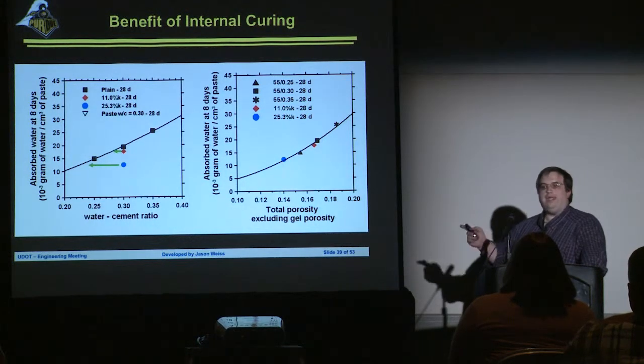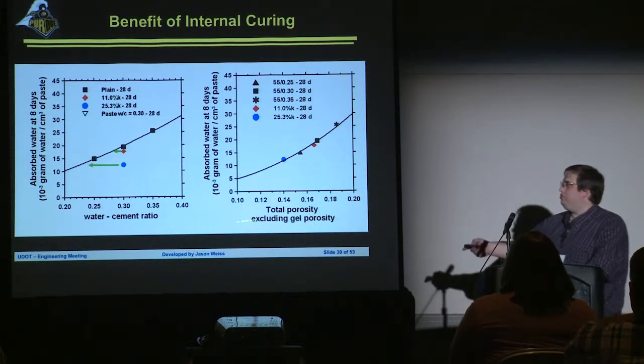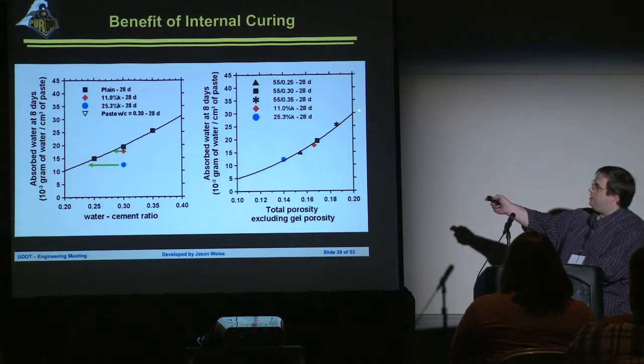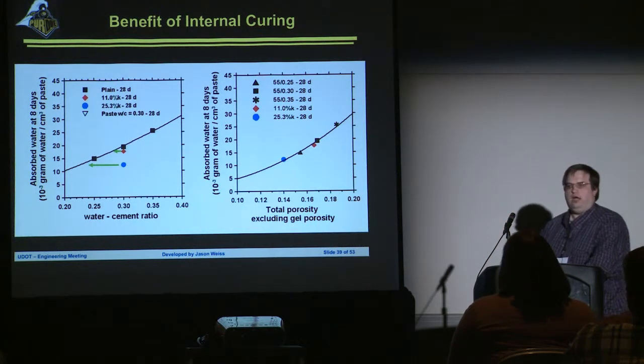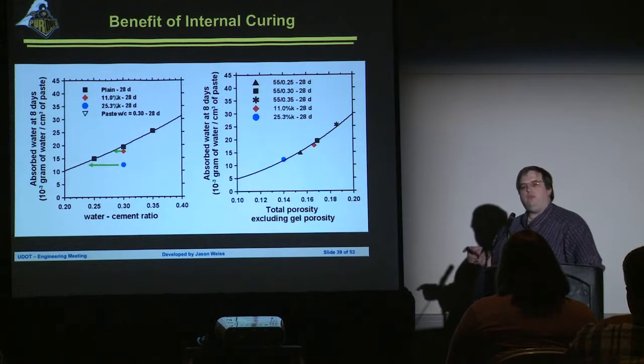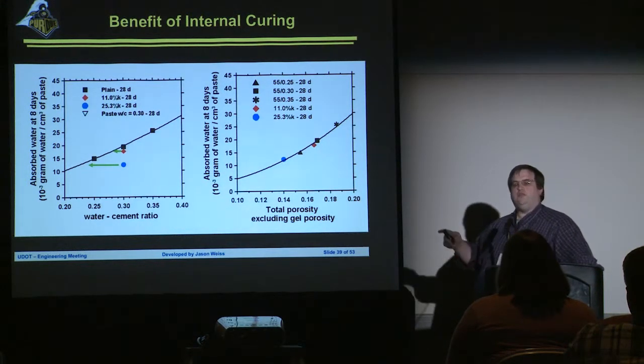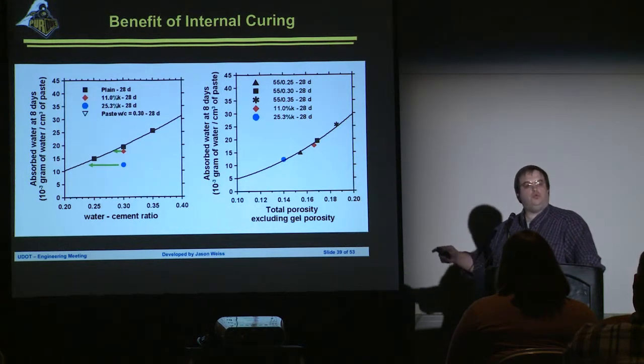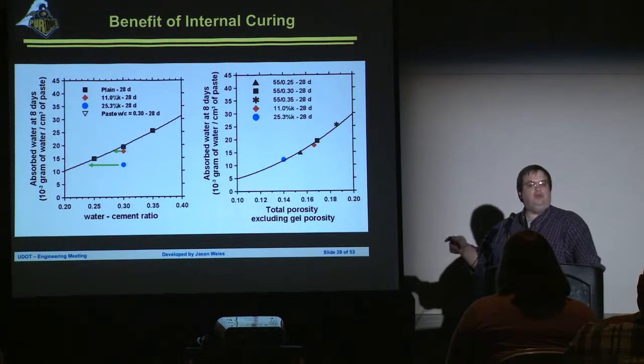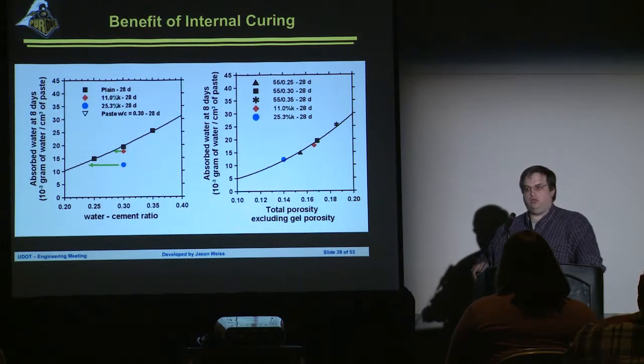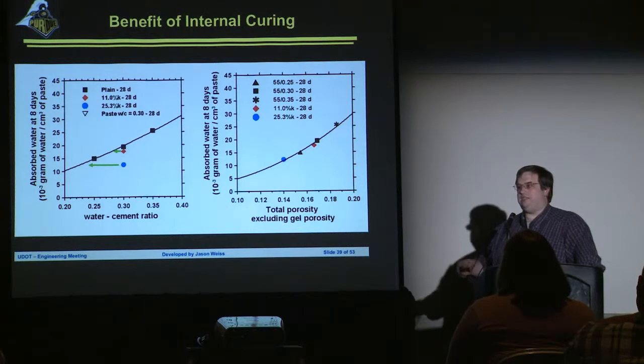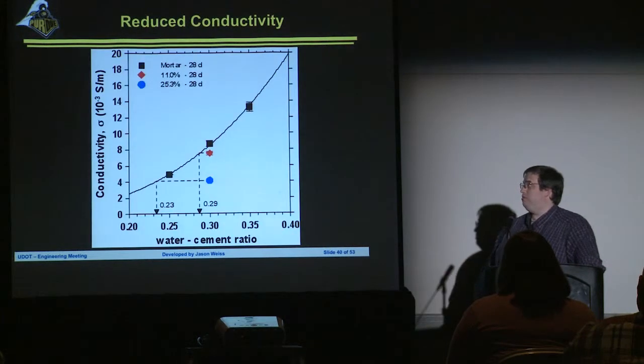Well, remember, we're hydrating more of the system. And if we measure the porosity, what we see is everything falls along a single line. So the benefit that we've got with internal curing is we've disconnected those porous regions at the aggregate interface and we've densified the structure. We've got less porosity in the system because we've hydrated more of the cement.